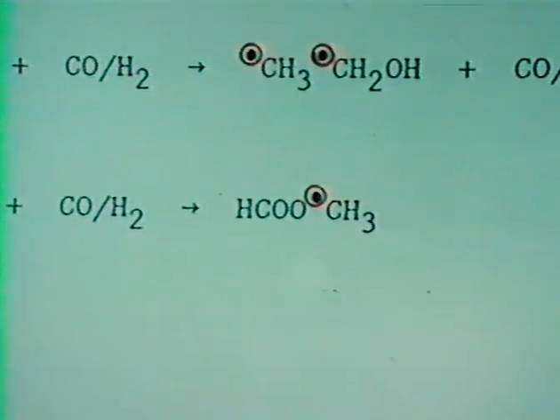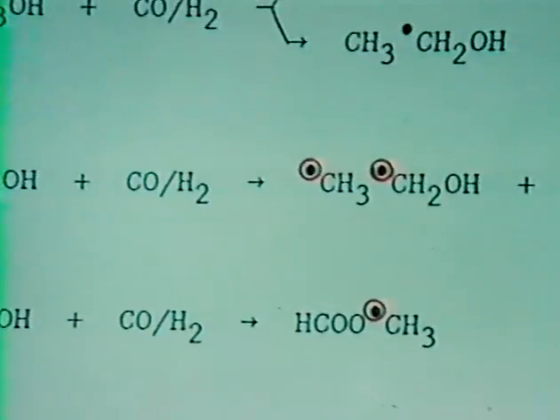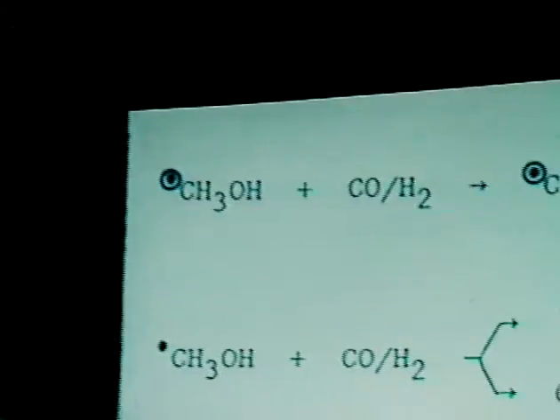The ethanol is formed by a different mechanism than methyl formate. Methyl formate is made by CO insertion, and ethanol by a coupling reaction. As one proceeds through the synthesis from C1 to C2, this was an unexpected result. One gets into the C2 to C3 step, and some of what we observed was expected, and some was unexpected.